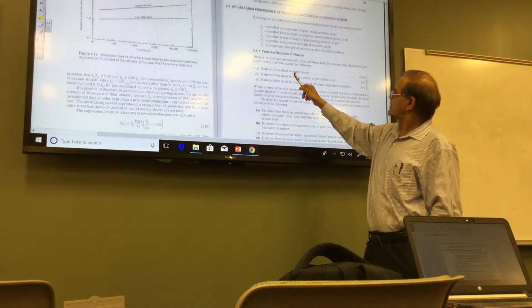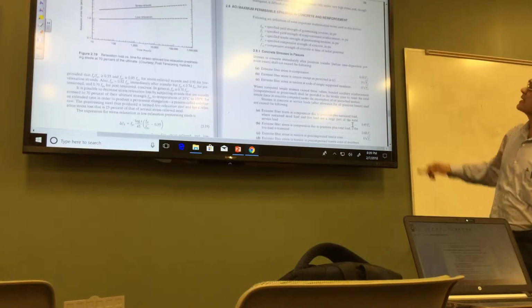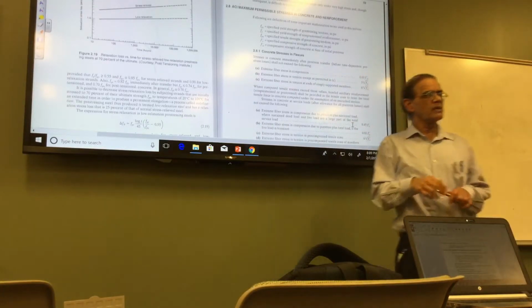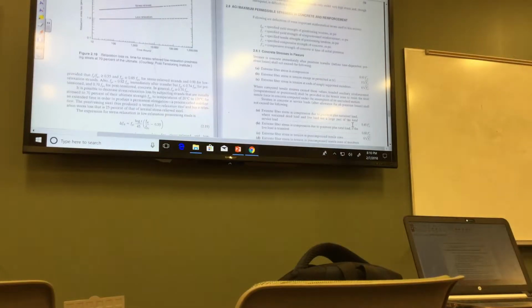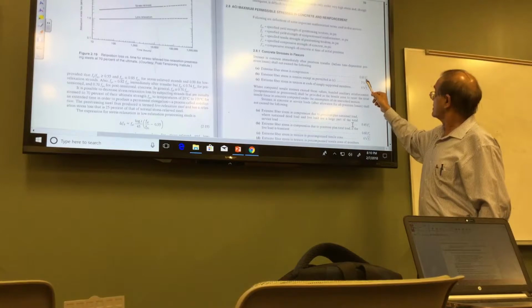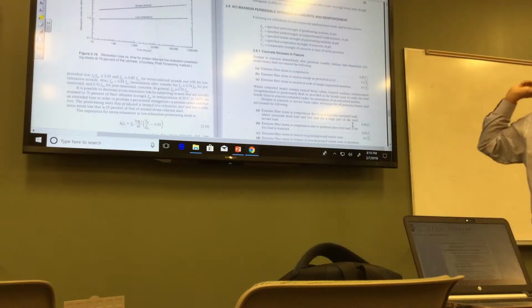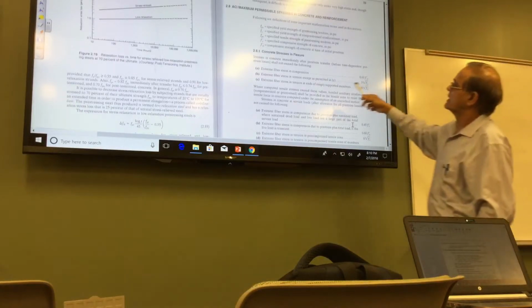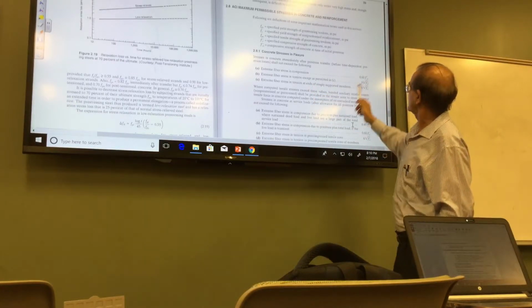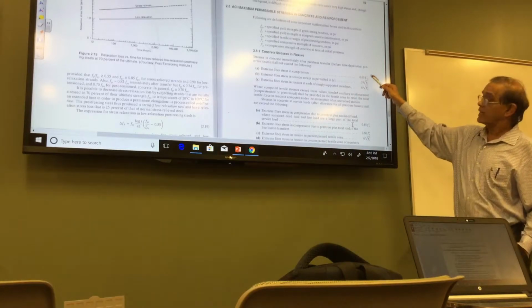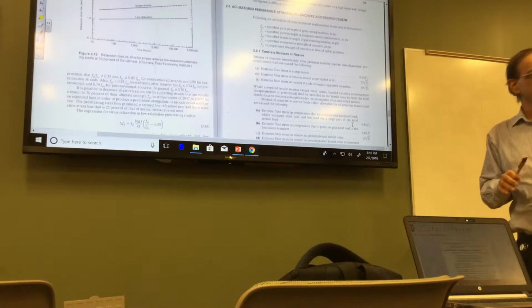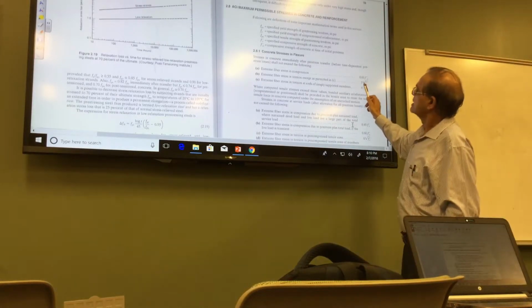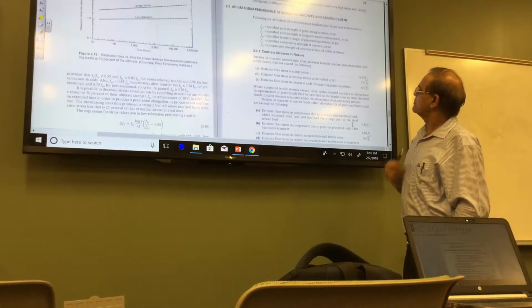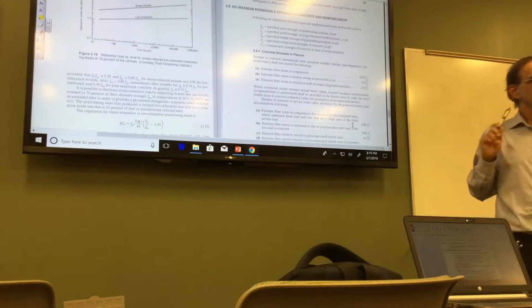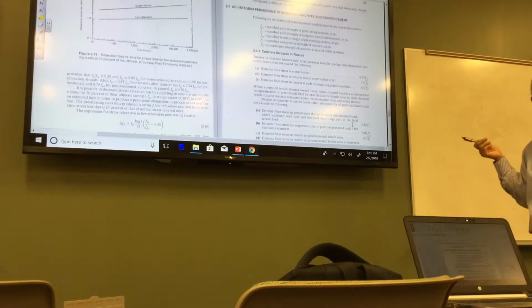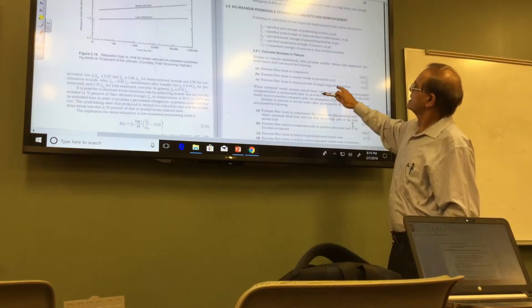So for example, extreme fiber stress in compression is 0.6 F prime sub CI in the initial stage. So for example, in your assignment, if you were to check the initial stage, then you would use 60%, if you knew this value, right? But we don't know in our case, so we don't know what was allowable, right? Extreme fiber stress in tension, except at the ends, is 3 times the square root of F prime sub CI, which is around 4,000 or 3,000 PSI, right? So that's 3 times that. But if it is extreme fiber stress in tension at the end of a simply supported member, then you go twice as much. So depending on what kind of member it is, you allow 3 or 6, right? Then this is the initial condition.